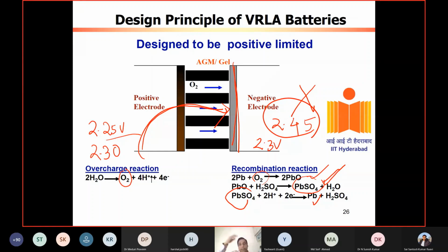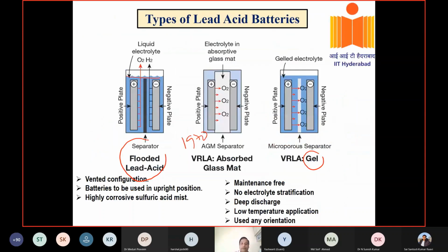That will automatically open in the... but if you add water, it is not going to absorb anymore, maybe a little in the top. It's not going to soak much of this water. So topping of water is not required for the VRLA system. It's completely maintenance free. You can go for deep discharge, that means you can go to zero, completely drain out all the capacity, and you can use any orientation. But the life is shorter. Here it is more. If it is 5 years, here it can be 2 to 3 years actually. The life is somewhat shorter.